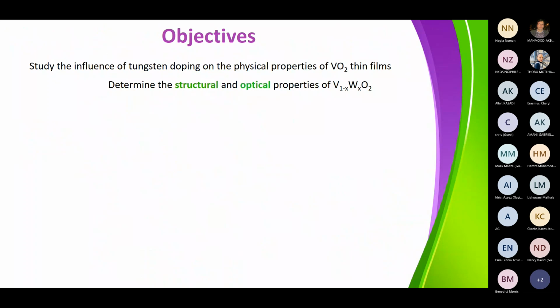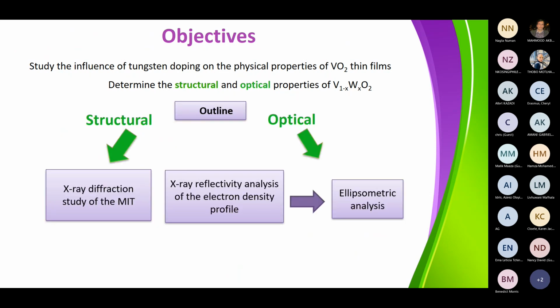And so the objectives of this study were to study the influence of tungsten doping on the physical properties of vanadium dioxide thin films, determining the structural and optical properties. And how do we do that? We did several types of measurements: X-ray diffraction measurements, X-ray reflectivity analysis of the thin films, and then finally, optical measurements by using ellipsometry measurements.